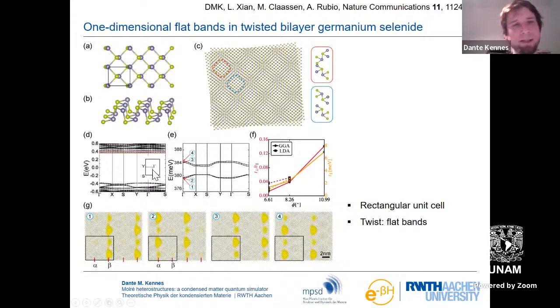And what that means is electrons do disperse along this direction. They do not disperse along the perpendicular direction. And that's one dimensionality. This is quantified a bit more in this panel F here. This is a twin axis, so I'll walk you through this. The x-axis shows the twist angle. So as we go to lower twist angle, the overall bandwidth decreases. This is shown as the yellow axis to the right here. This is the overall bandwidth, called T parallel here. Or the overall bandwidth is proportional to T parallel, one should say. And as you see, this goes down to smaller and smaller values as you go to smaller twist angle.